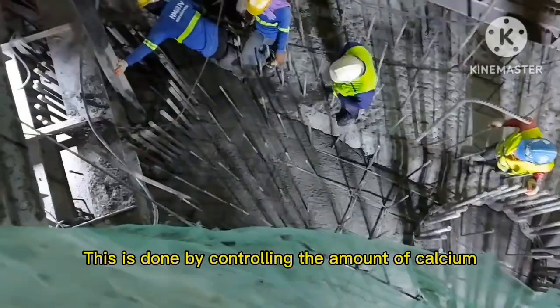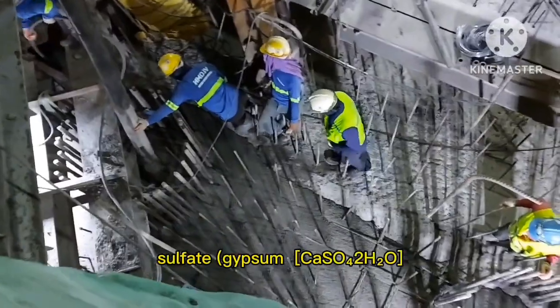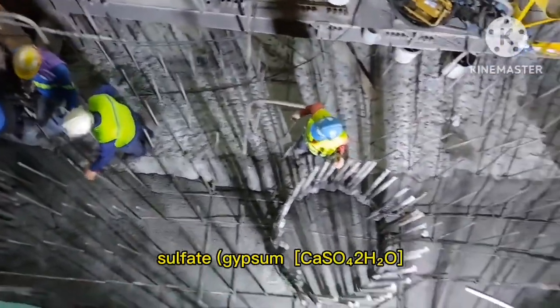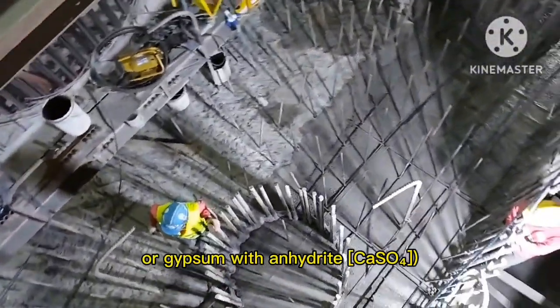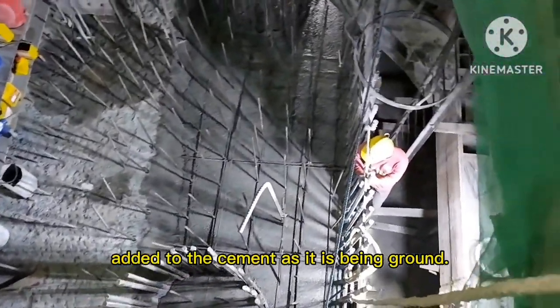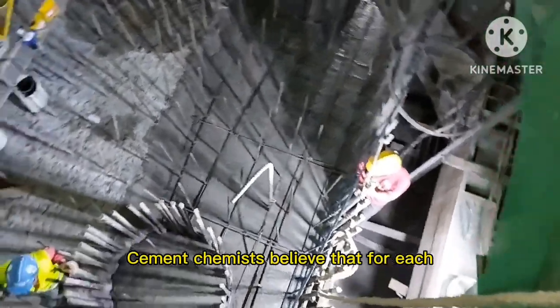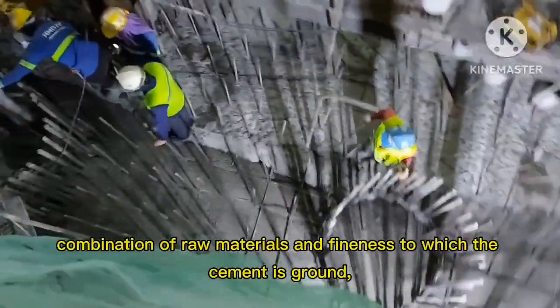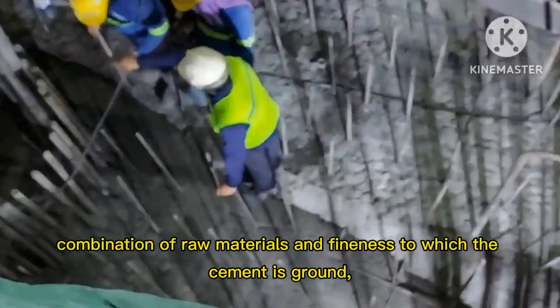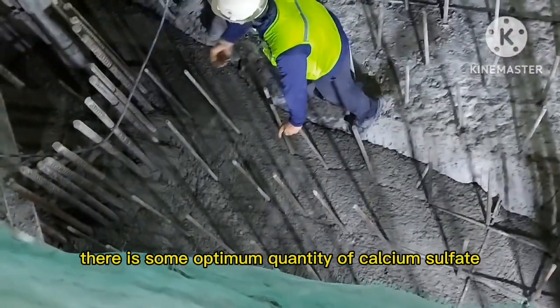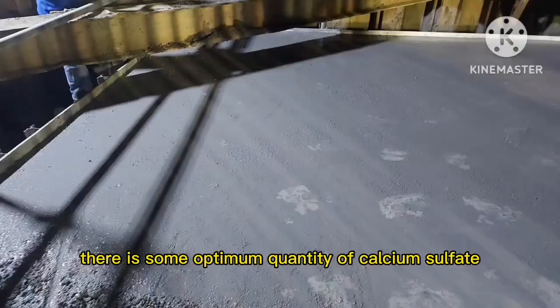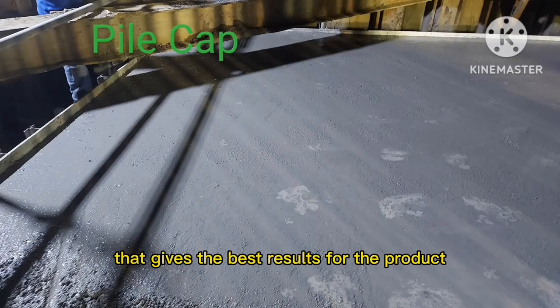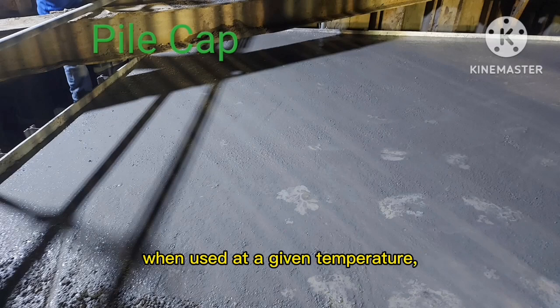This is done by controlling the amount of calcium sulfate, gypsum (CaSO₄·2H₂O) or gypsum with anhydrite (CaSO₄), added to the cement as it is being ground. Cement chemists believe that for each combination of raw materials and fineness to which the cement is ground, there is some optimum quantity of calcium sulfate that gives the best results for the product when used at a given temperature.